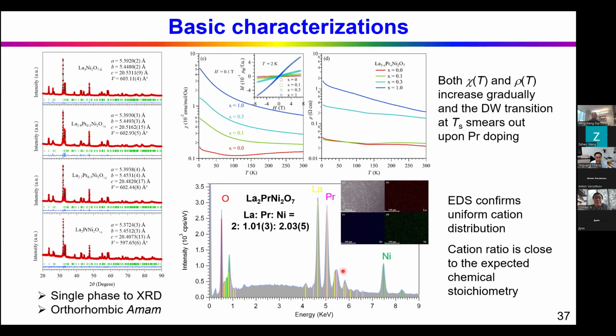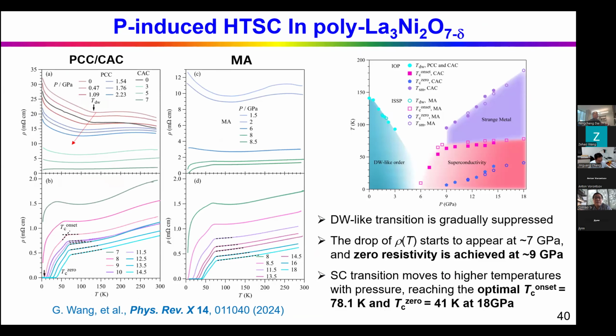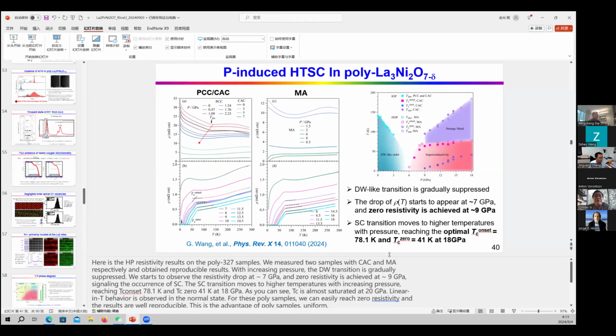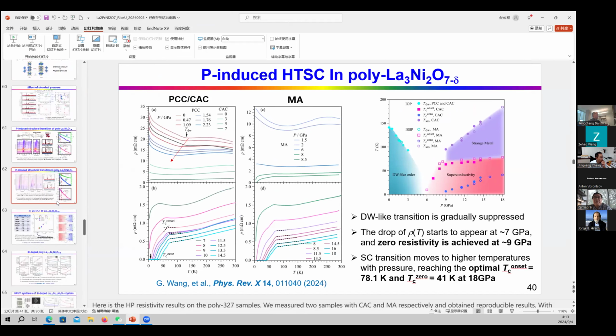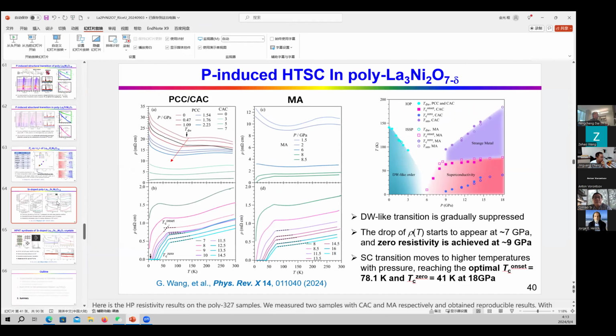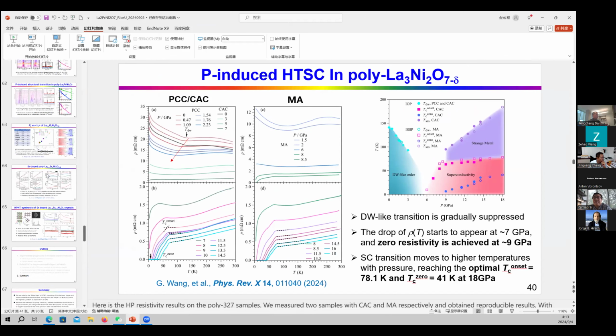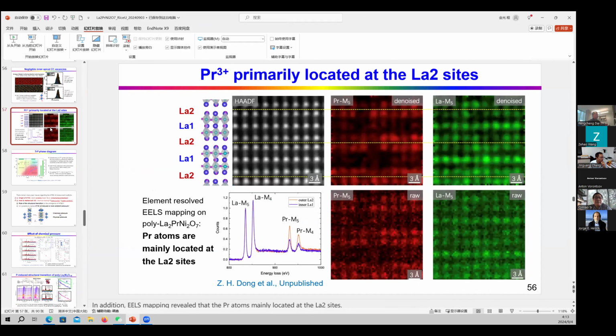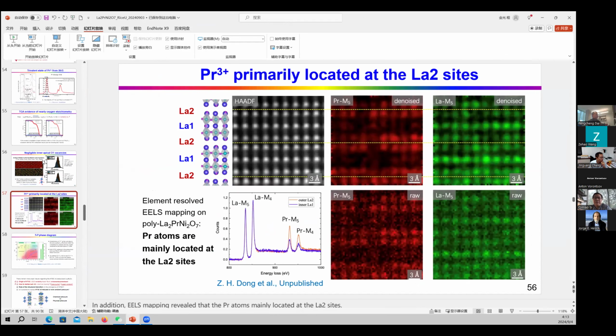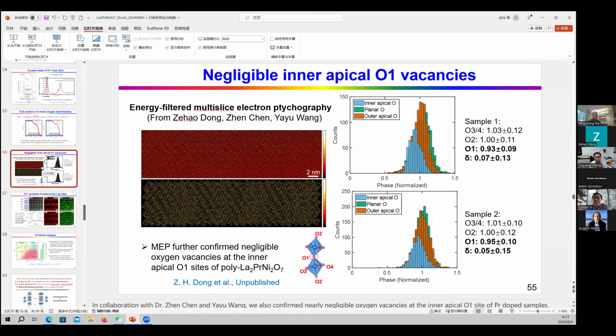Any other question for Jinguang? So I guess basically what you find is that the structural distortion. Are you claiming that the oxygen O1 site fully filled is actually better for high Tc? Is that the takeaway message? You said in the pristine doped sample the oxygen O1 site vacancy is actually less, right? Typically people thought to remove apical oxygen is good for high Tc, right? You're saying that in this case having a filled O1 site in the doped sample is actually better for Tc. Yes.